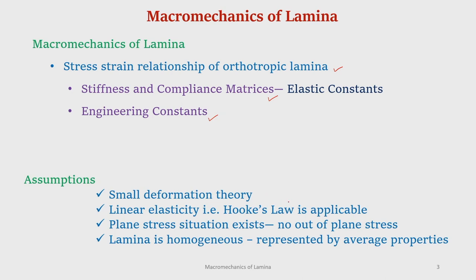We will consider that it is linearly elastic, that means Hooke's law is applicable. We will use the small deformation theory, that means the strain displacement relationship for small displacement holds true here. And because the lamina is thin, we can consider that a plane stress state exists and no out of plane stresses are there. And very, very important, because it is macro mechanics analysis, the lamina is considered to be homogeneous.